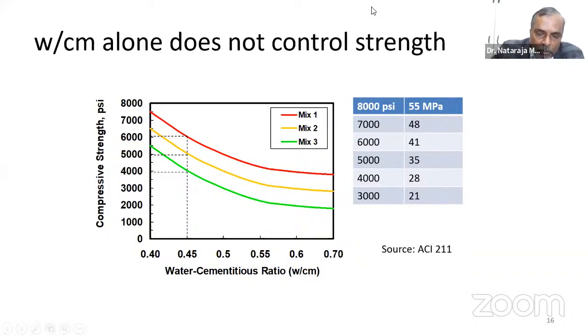But when you start using supplementary cementing materials along with the cement, even with 0.55, 0.6 and 0.7 water cement ratio, my dear friends, and if you see these strength ranges, 2000 to 3000 PSI. This is the graph I have taken from the American Concrete Institute 211 code, which is available on the internet. And kindly see that 3000 to 5000 PSI is nothing but concrete having a strength of 20 to 35 Newton per mm square.